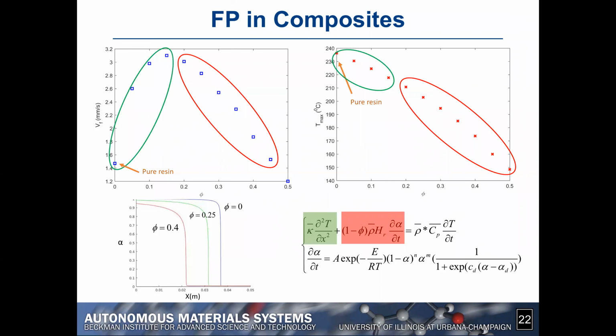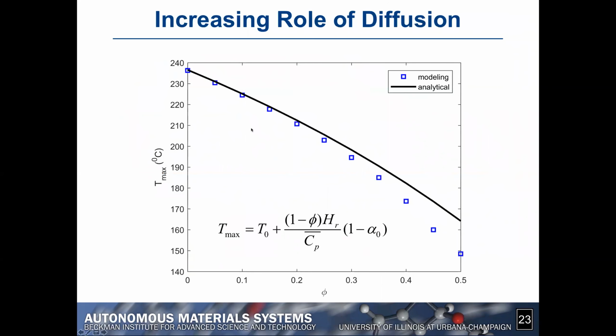So now, we can quantify the increasing role of diffusion by comparing the numerical values that I just presented for the maximum temperature as a function of the fiber volume fraction, these are the square symbols, to the very simple analytical relation that we obtained right over here, which ignores completely the role of diffusion. If we compare these two, we can see that the analytical expression follows the numeric one very nicely, except when you start to increase the fiber volume fraction to values in excess of 0.3, let's say. They start to deviate from each other, and that's really due to the increased importance of diffusion associated with a larger amount of fibers in the system.